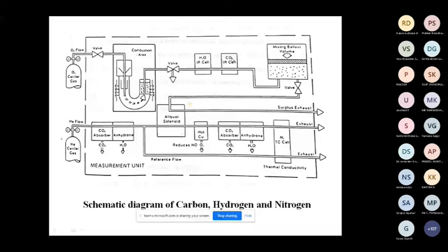An aliquot of the sample is taken. It will pass through copper, where the NOx is converted into nitrogen. Then finally nitrogen is measured by thermal conductivity. So here we are measuring the hydrogen content, here the carbon content, and here the nitrogen content. That's the instrumental technique for carbon, hydrogen, nitrogen. Per sample, it will take a minimum of 12 minutes. Per sample, carbon, hydrogen, nitrogen determination takes 12 minutes. This is the instrument we got at BHEL.